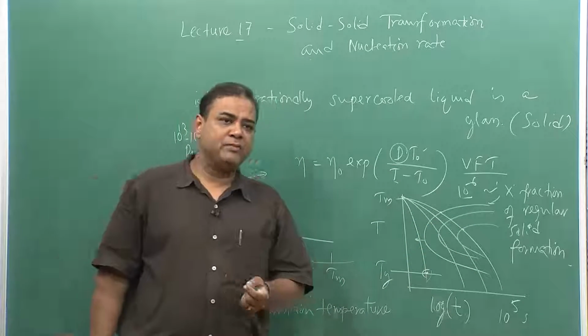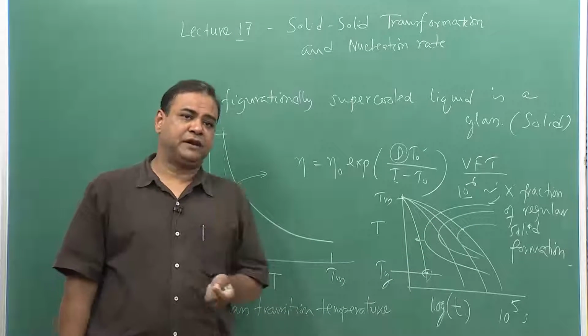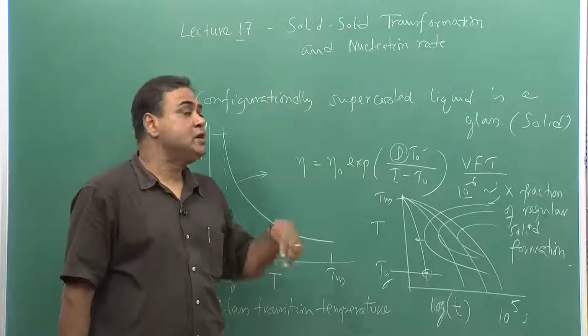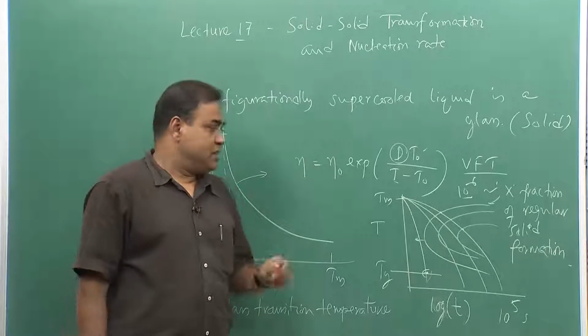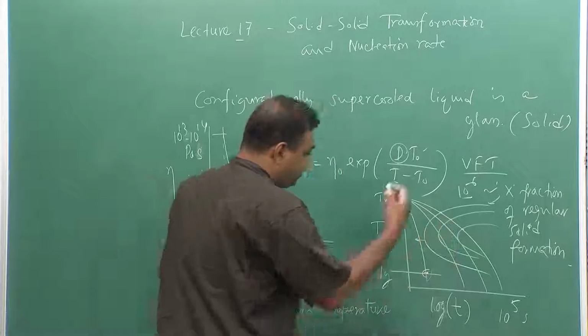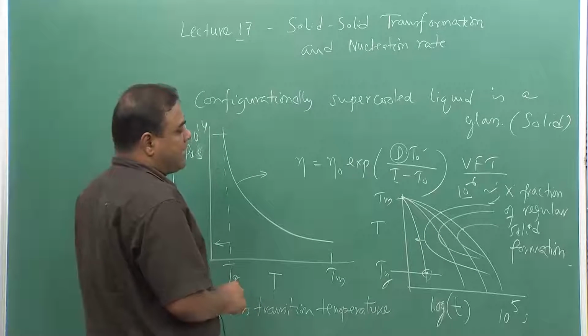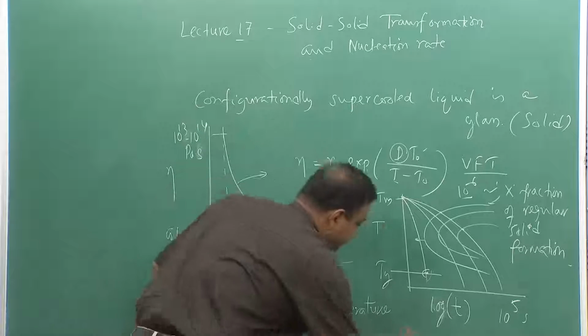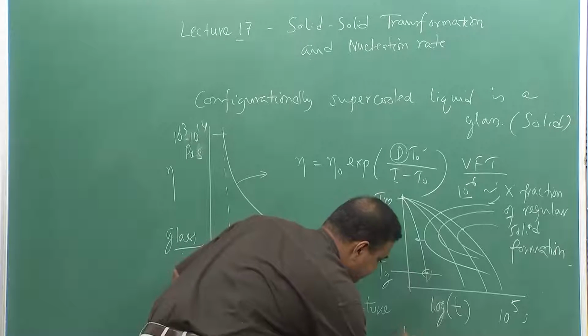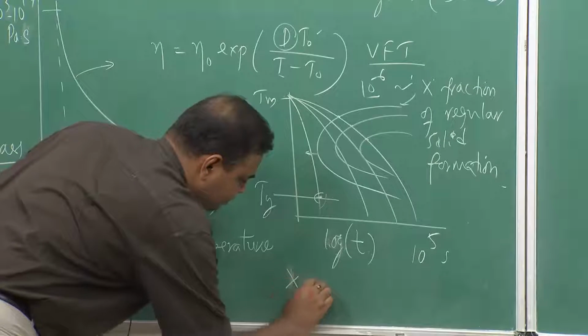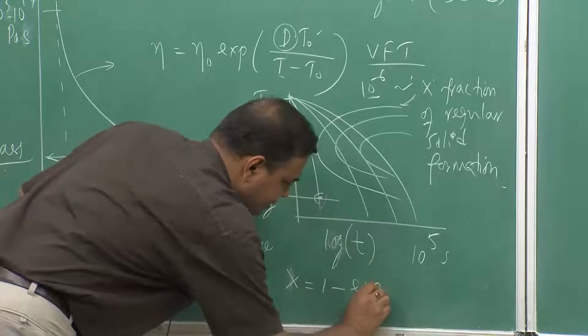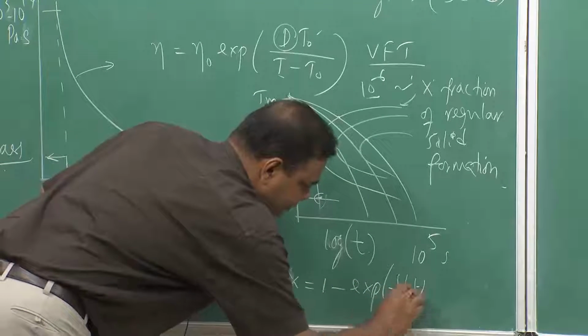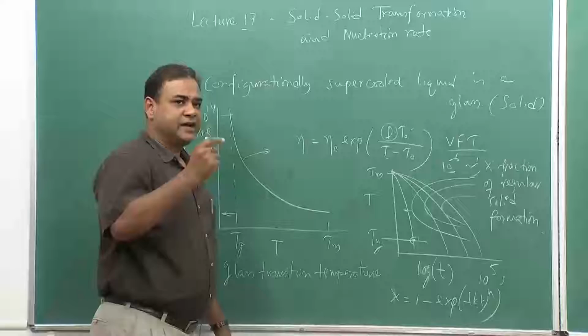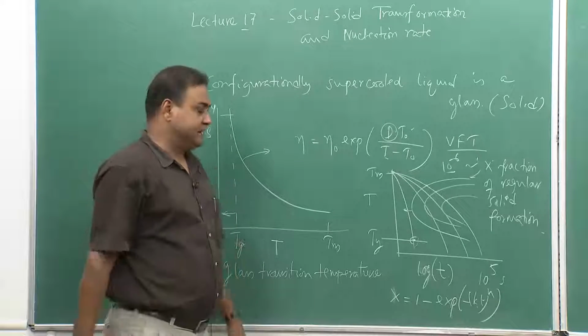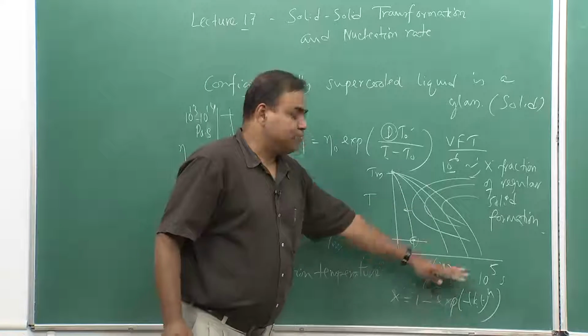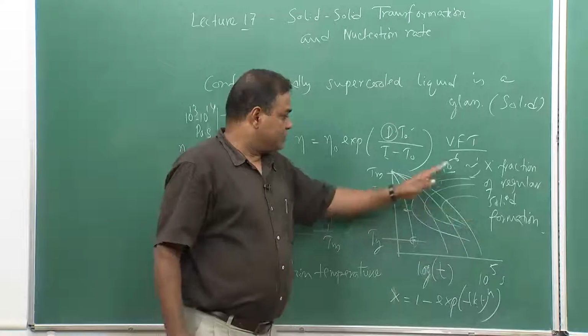Of course, there will be one more parameter which will be needed, that is the growth rate. So we will come across that growth rate once we consider the nucleation rate. If you go back to earlier lectures, you might have seen this particular expression, x equal to 1 minus exponential minus kt to the power n, where k involves I as well as u. U is the growth rate, and that is what we need to measure, I as well as u, in order to get this TTT diagram.